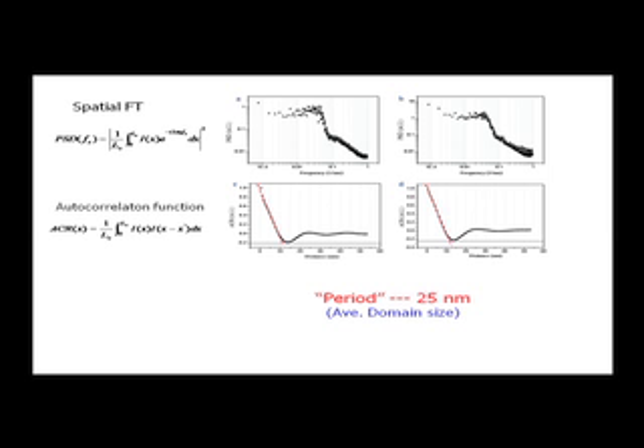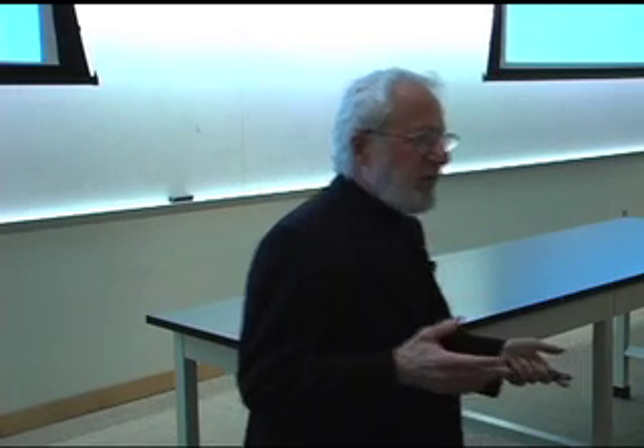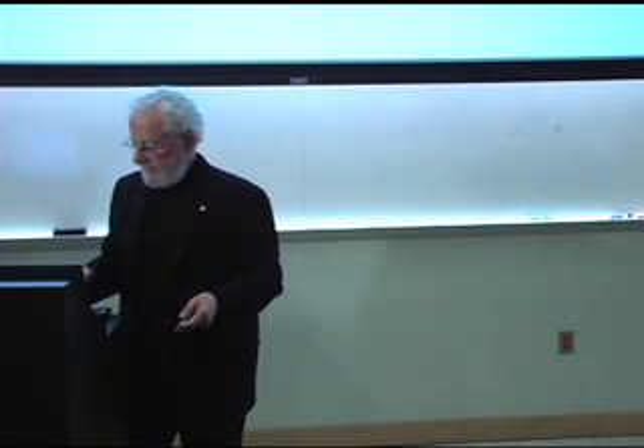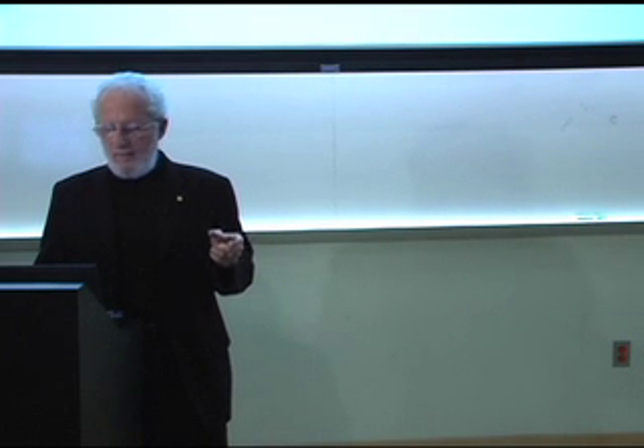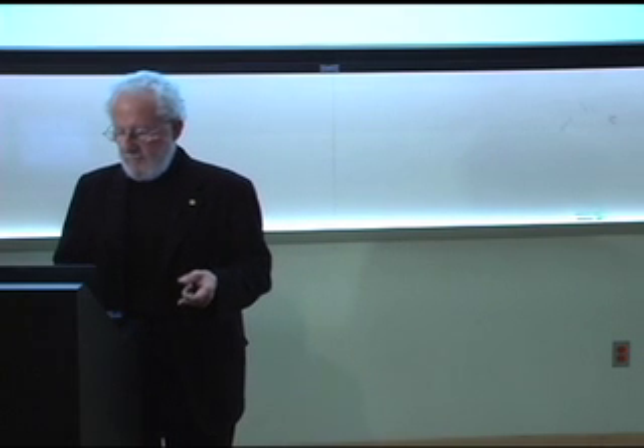And there is. So it falls off here with, as you can see, in nanometers, 10, 15 nanometers. The repeat length is about 25 nanometers, and we've seen this kind of thing now in several systems. Okay? So those are the typical numbers, 20, 25, 30, and I'm sure this isn't one number, but a distribution of numbers on that scale. That's the length scale that the phase separation forms spontaneously.